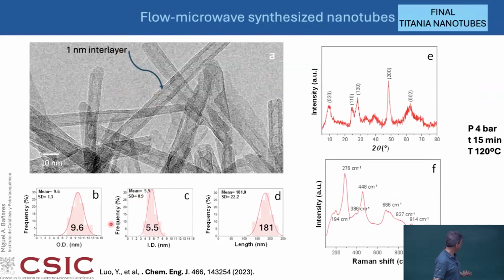And what you can get is a very accurate control, like you can see here, about 9 or 10 nanometers in the outer diameter, and the internal diameter, so the opening, the lumen inside, is about 5 nanometers, and the length is also rather constant, around 180 nanometers long.